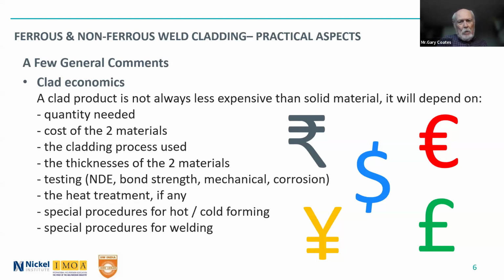Obviously, if you want 3 millimeter of one material and 3 millimeter of another material, the total cost may be more than if you use solid material. With clad, you have a lot more testing involved, a non-destructive examination. You may have to test the bond strength. You might have to do special mechanical tests to make sure that it is suitable for the application. And corrosion, if you do a heat treatment, you might want to make sure that the corrosion properties have not deteriorated through the heat treatment.